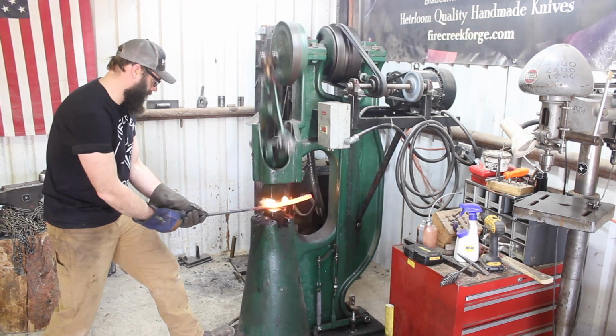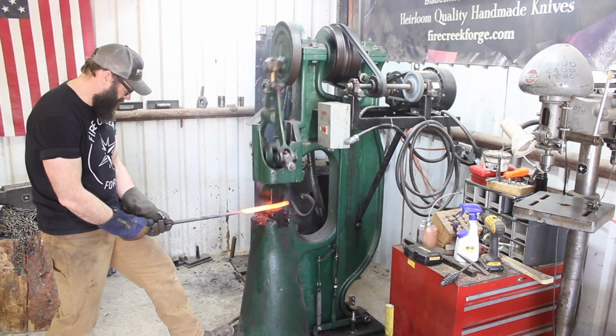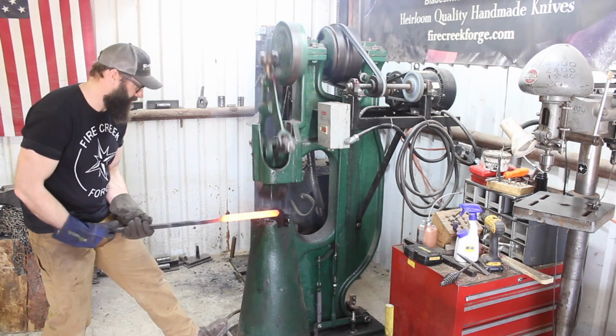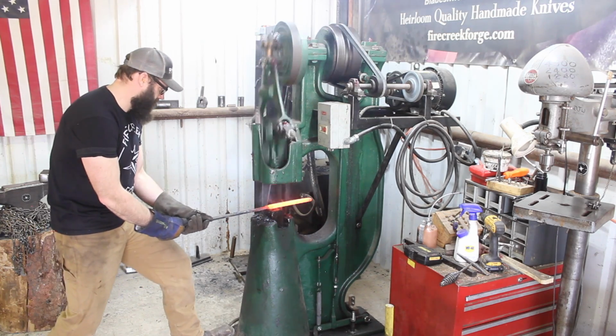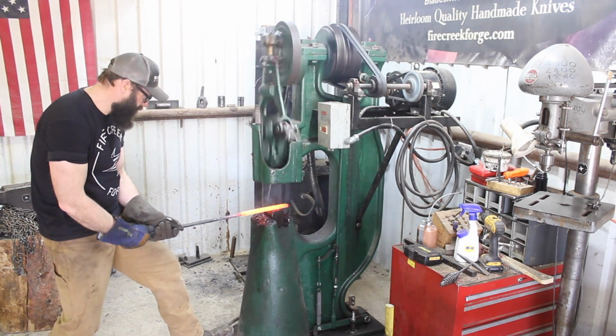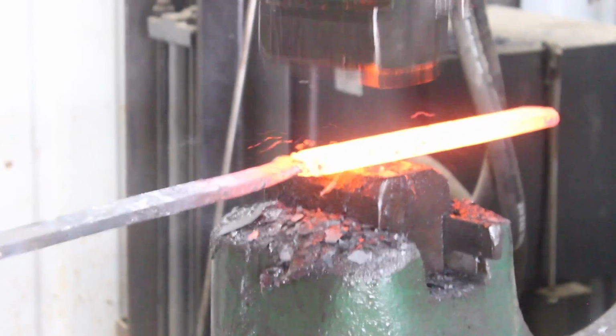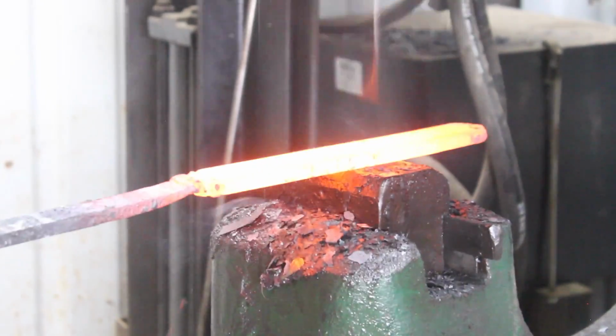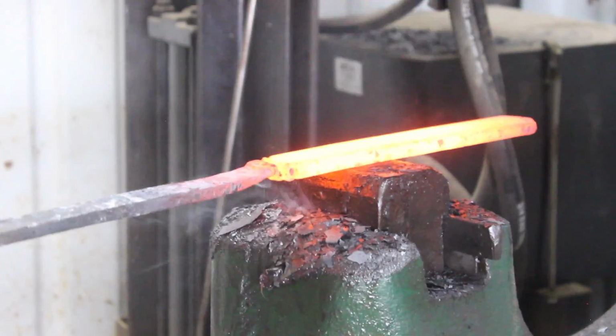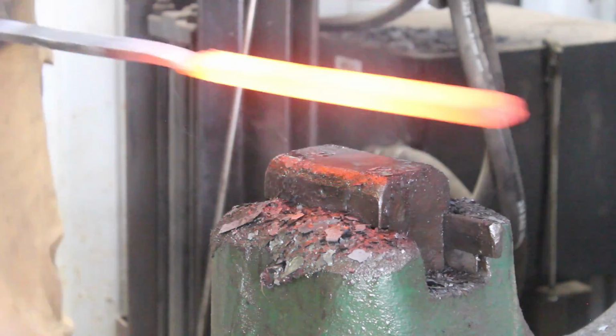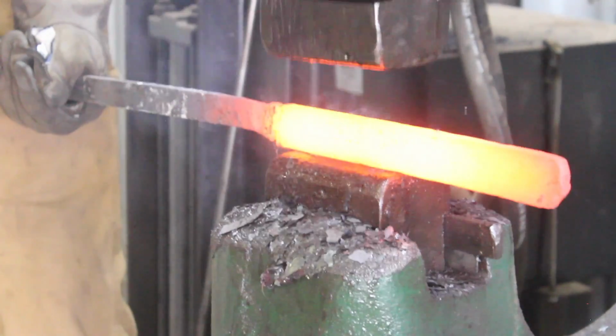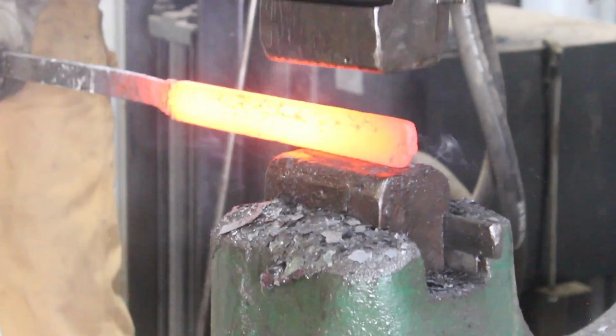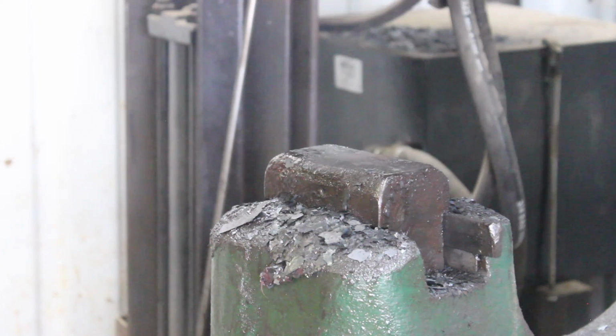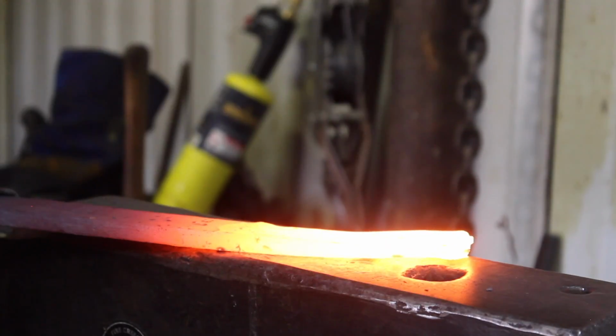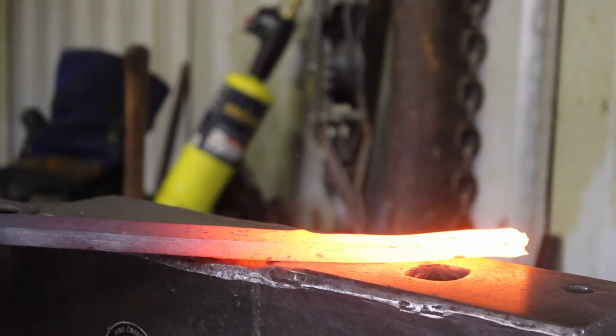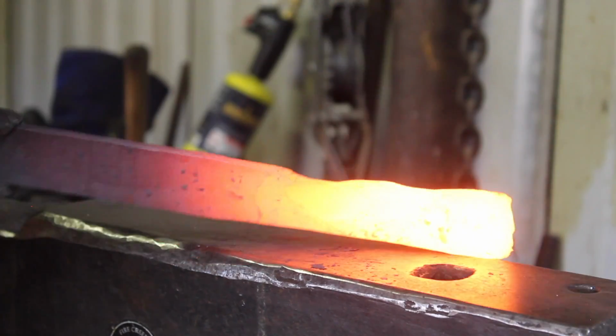But the power hammer is limited in the size of cross section that it can effectively work. So that's why having this variety of tools is very beneficial if you're doing this kind of thing all the time. I want to work my billet equally on both sides as much as possible, and that will help the center steel stay centered so that when we go to finish and grind our blade, we have equal reveal on each side of the blade instead of having things off center.